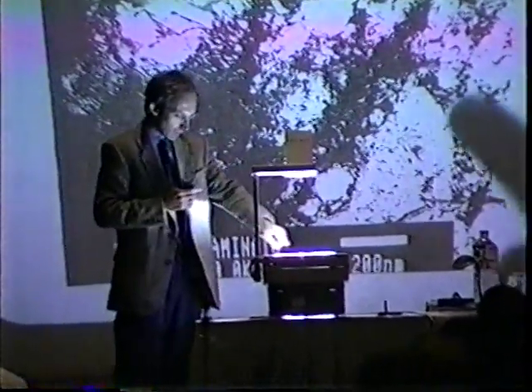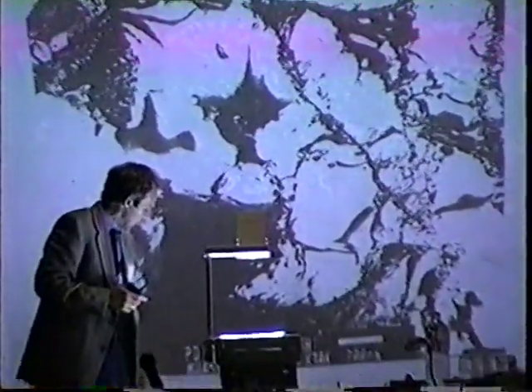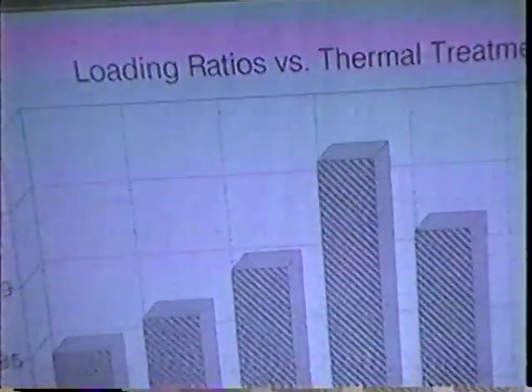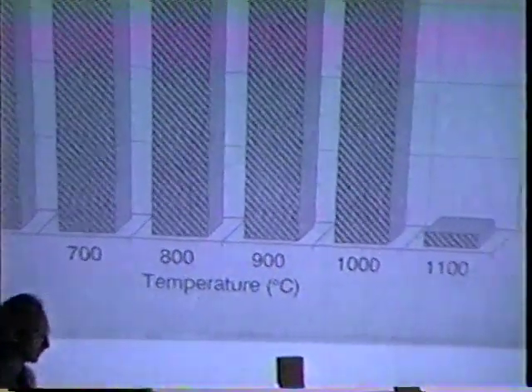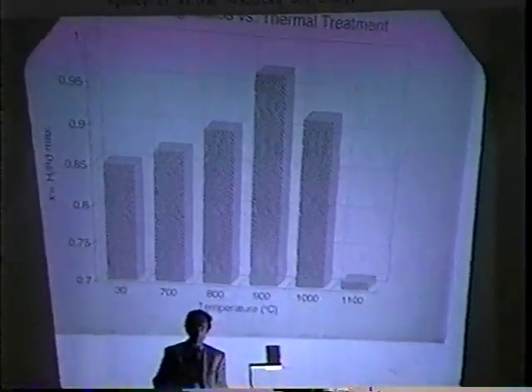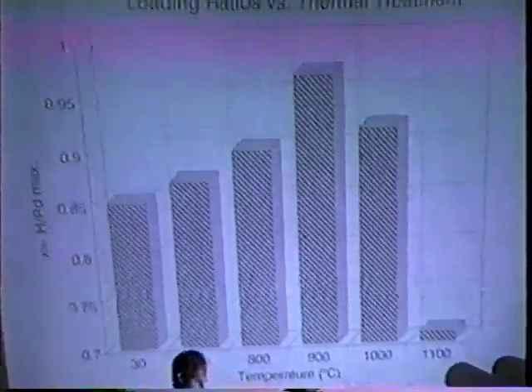This is a simple cold work in palladium, and you can see a large concentration of defects. This one is material after cold work plus annealing at 800 centigrade for 4 hours. You can see these pathways for hydrogen diffusion in the bulk. And here we have the material after 5 hours at 1100 centigrade. You can see that the pathway disappears and the grain grows up again. And this is the behavior of such investigated materials. So you can see the loading ratio against the treatment. And we had a maximum above 0.95 at 900 centigrade annealing after cold work. Thank you.